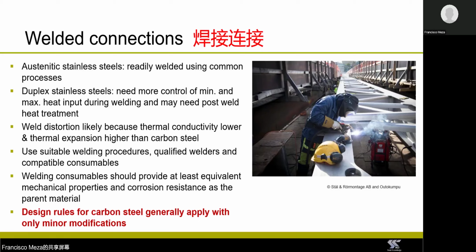Now, duplex stainless steels, on the other hand, need tighter control during welding, and in particular, the welding procedure needs to control both the minimum and the maximum heat input, because the welding thermal cycle can affect the phase balance of the material, which can affect the mechanical properties and the corrosion resistance of the welded zone. So you might need to carry out a post-weld treatment in order to restore the full corrosion performance of the welded zone.